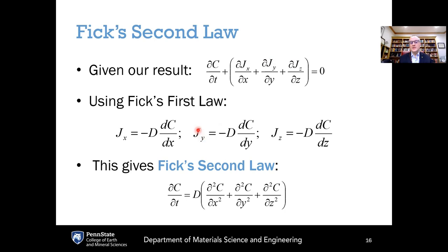The flux in the y direction is minus the diffusion coefficient times the concentration gradient in the y direction. And analogously, in the z direction, the flux in the z direction is minus the diffusion coefficient times the concentration gradient in that z direction. So using Fick's first law and substituting this into this equation where we see the jx, the jy, and the jz, the common factor of minus D can get pulled out in front.